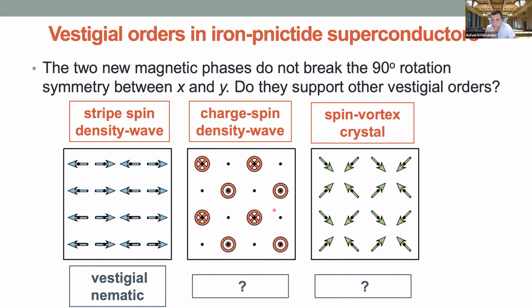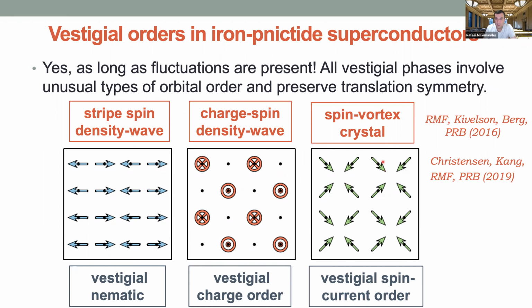Now, that actually brings the question, if these two other phases are realized, do they also have a vestigial phase? Remember that the striped spin density wave breaks the equivalence between X and Y, the 90-degree rotation. What about these other two? Do they have any sort of vestigial phase? You can see immediately that they don't break tetragonal symmetry, they don't break the equivalence of X and Y. So if there's a vestigial phase, it'll be something else. And actually, in both cases, they do, as long as fluctuations are present.